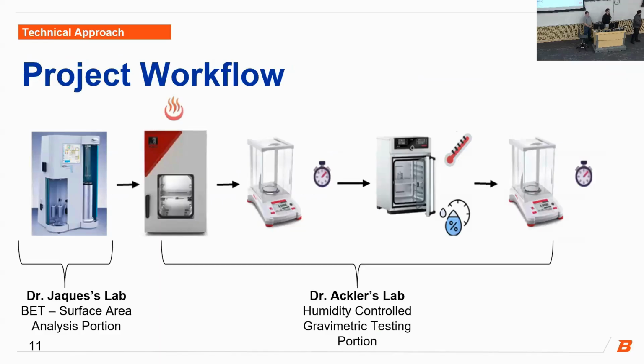Switching over to the technical approach, we first wanted to show you an overview of our entire project workflow. We start this work in Dr. Jaquez's lab with the BET surface area analysis portion, and then we transfer over to Dr. Ackler's lab, where we do the humidity-controlled gravimetric testing, which consists of the vacuum oven dry, the exposure in the humidity chamber, and weighing at allotted periods of time.